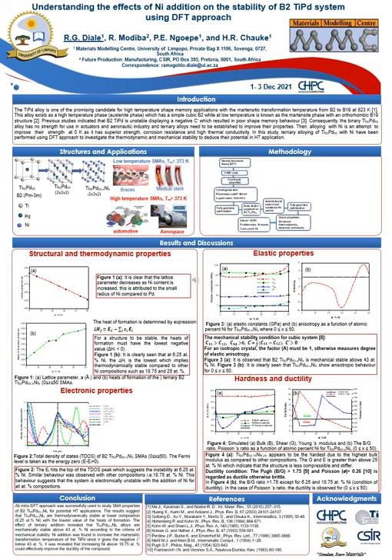Furthermore, we checked the thermodynamic properties by looking into the heat of formation. We found that the heat of formation increased with an increase in nickel. We suggest that the thermodynamic stability is not enhanced in this case with the addition of nickel.